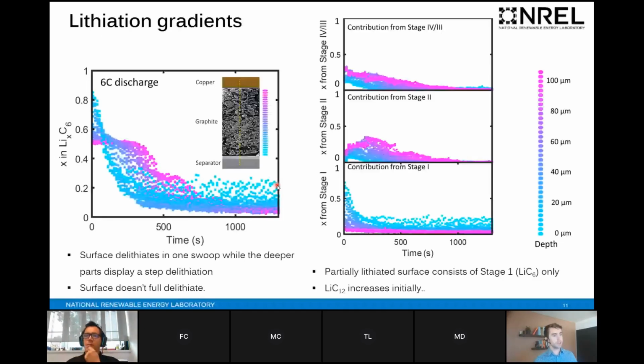And we can get some insight into what's causing this. So we can see a reduction in stage 3 generally. We see an increase and decrease of stage 2 that's caused by stage 1 transitioning to stage 2 initially, so we see an increase, and then stage 2 transitions to stage 3, so we then see a decrease. And we see that all of the lithiated state close to the separator is in the form of stage 1, and it only correlates with where we saw lithium plating. So we saw coexistence of LiC6, full lithiation, where lithium plating is present, and we think that's due to the lithium plating keeping the regions directly underneath in a fully lithiated state, even upon discharge.